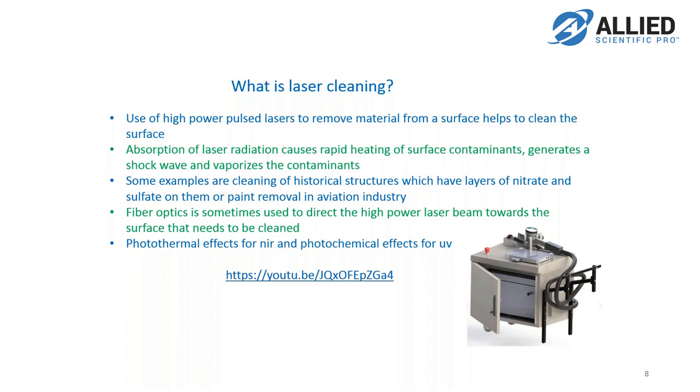So you'd use a laser cleaner. Absorption of laser radiation causes rapid heating of the surface contaminants, generates a shock wave, and vaporizes the contaminants. Some examples are cleaning historical structures, which have layers of nitrate and sulfate, or paint removal in aviation industry. So if you use a near IR laser, the effect that you'll be using would be photothermal. So just evaporation and basically plasma generation, shock waves. And if you use a UV laser, such as the one that I mentioned, the excimer laser, there will be photochemical effects, which dissociate molecules.